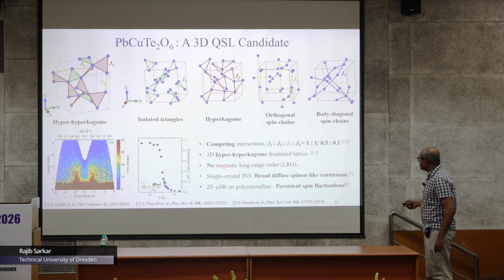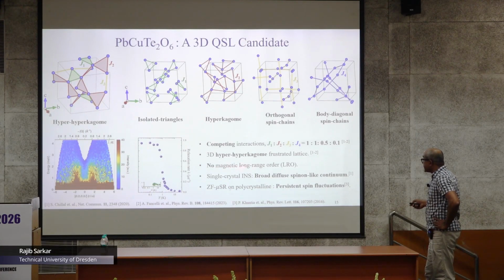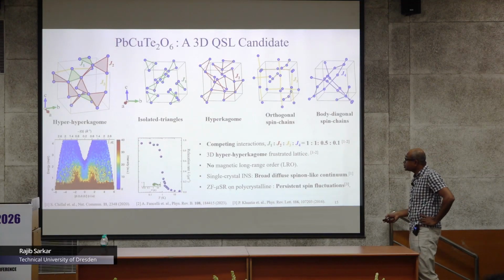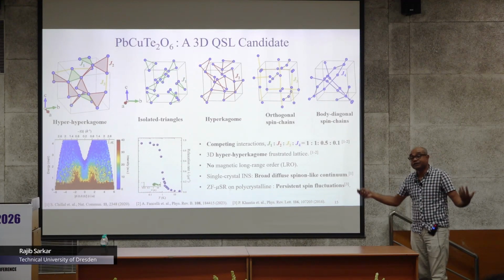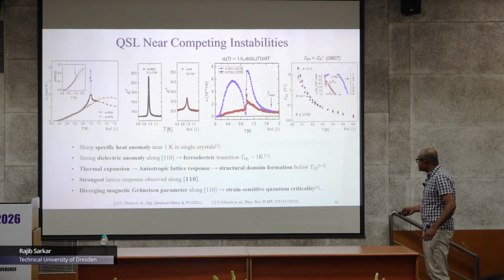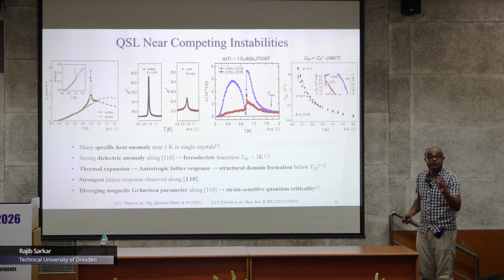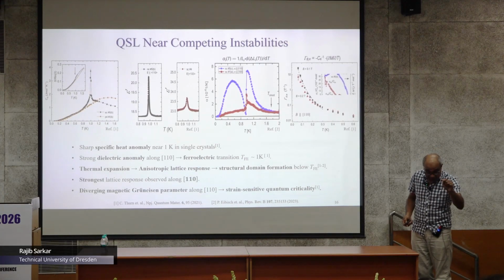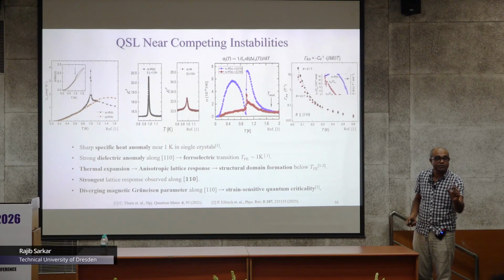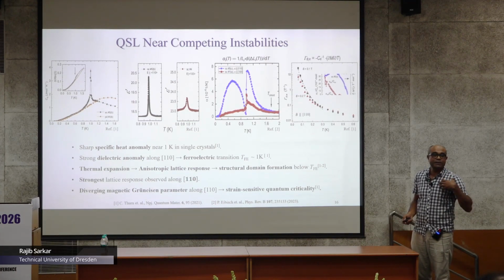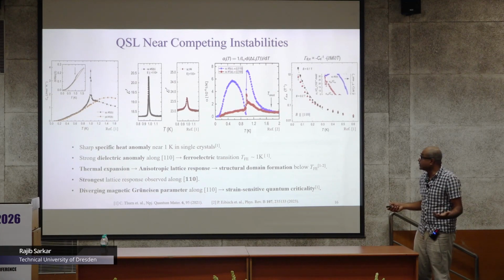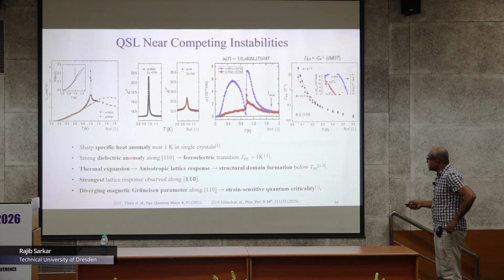It shows basically no magnetic long range order down to at least 50 millikelvin, and the muon spin rotation shows enhancement of the spin lattice relaxation rate and persistent spin dynamics, and neutron scattering also shows some kind of diffuse scattering. Not only that, very beautiful single crystals are available, and this is where we are headed, because finding a good single crystal is important for the experiments we do.